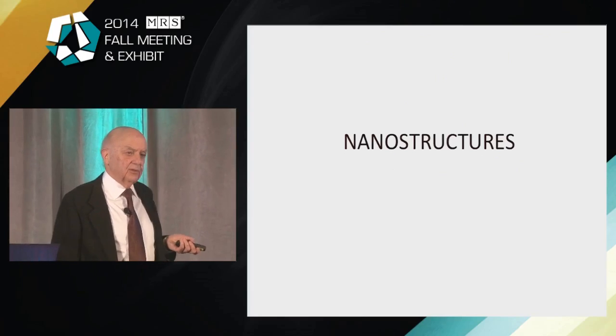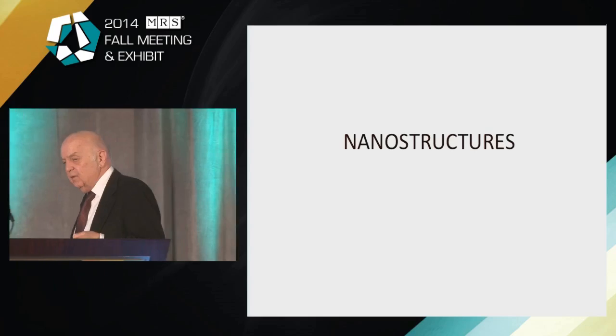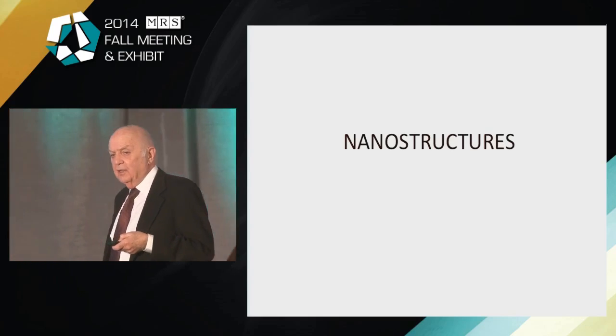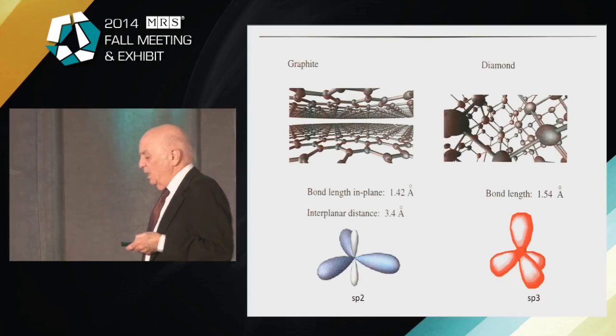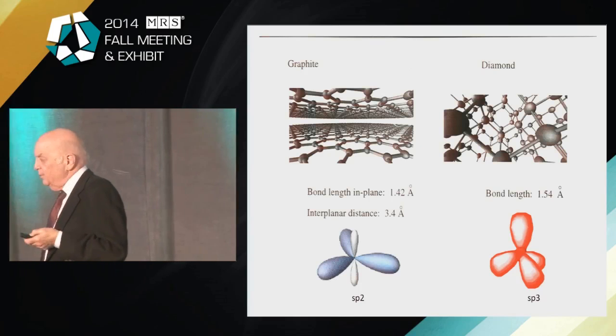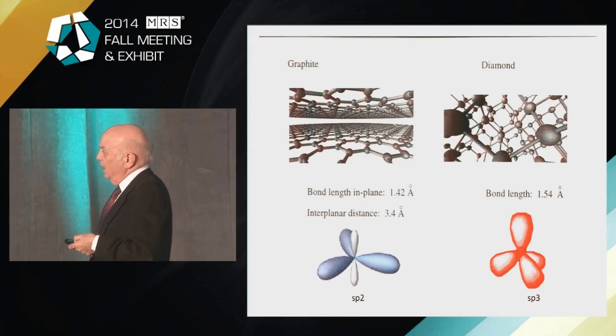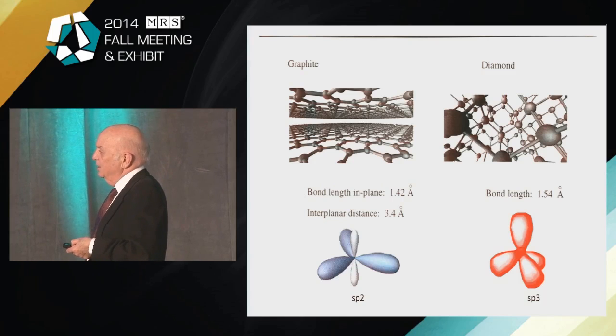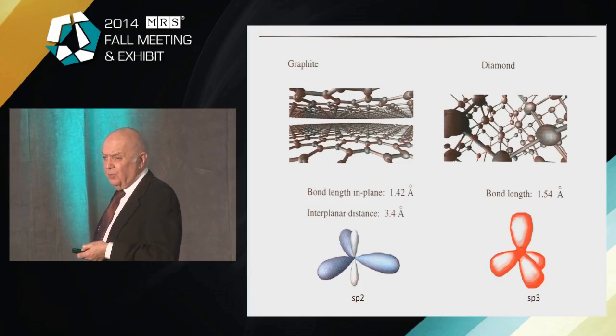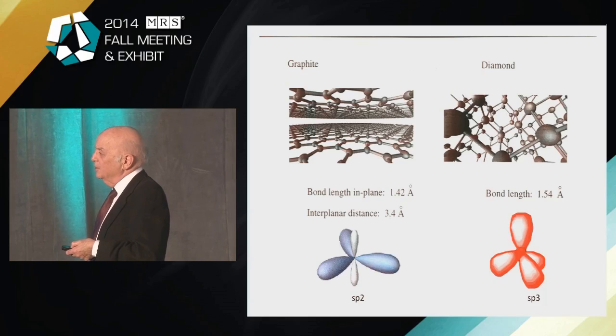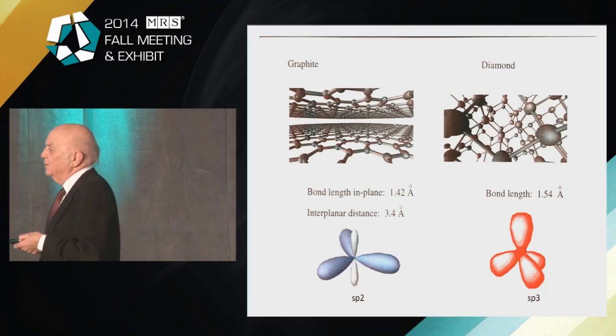Another one would be in the nanostructure range. There's a great deal of work being discussed here about nanostructures, nanotechnology. And again, these methods work. So for example, we talked about diamond, where every carbon atom is surrounded by 4 other carbon atoms at a distance of 1.54 angstroms. But carbon, because of this peculiar bond structure, you can actually make 3-fold coordinated carbon. Every carbon atom has 3 neighbors. This is the so-called sp2 structure.